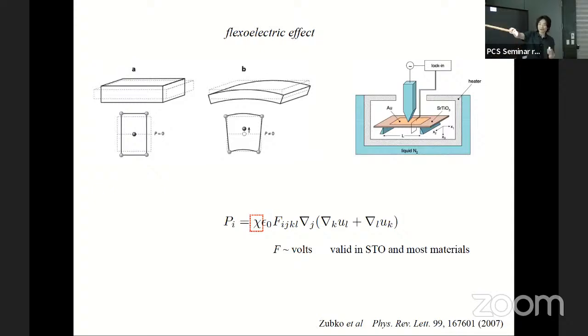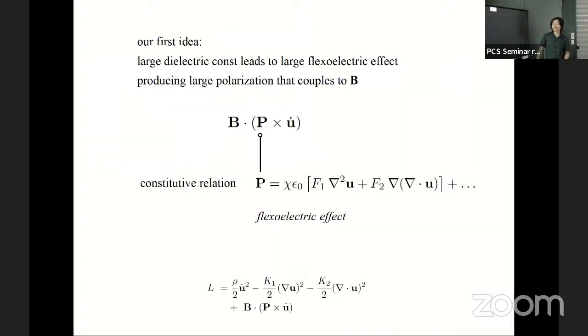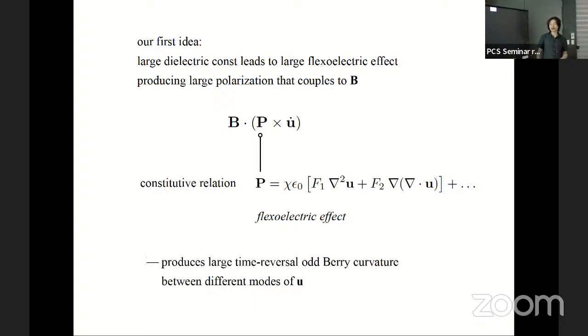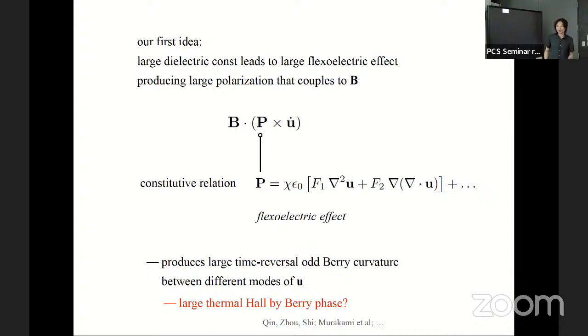So the large dielectric constant leads to a large flexoelectric effect, and the physical picture is very intuitive. Then it comes back to here. It will generate a large coupling of the phonon to the magnetic field. So maybe this will produce a large time reversal odd Berry curvature. The Berry curvature arises when different components of u are mixed and you need to re-diagonalize the Hamiltonian or the Lagrangian. So this will couple strongly to the magnetic field, and it will generate some large Berry curvature for the longitudinal and the transverse modes of the acoustic phonon. Because this Berry curvature is time reversal odd due to the magnetic field, maybe it will generate a large thermal Hall effect.